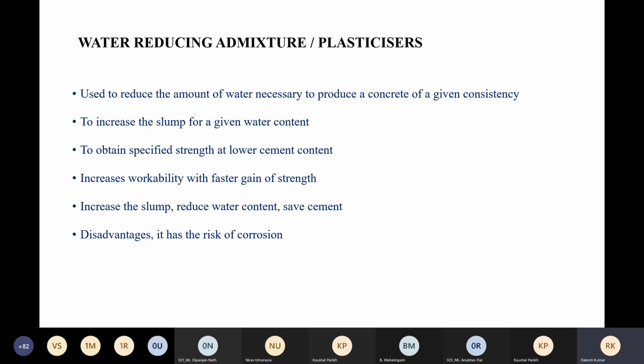Now, water reducing admixtures are plasticizers used to reduce the amount of water necessary to produce a concrete of given consistency. Because for the workability, the slump is necessary. So to increase the slump for a given water content, if you use the water reducing admixture and you fix the water cement ratio, certainly slump will increase. To obtain a specific strength, a lower water cement ratio, as per Abrams' rule, if you want more strength, the water cement ratio should be less. Increased workability with faster gain of strength, increase the slump, reduce water content, save cement. That is another purpose. You can save the cement.